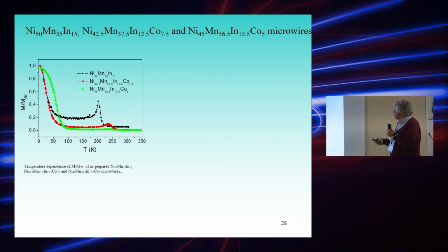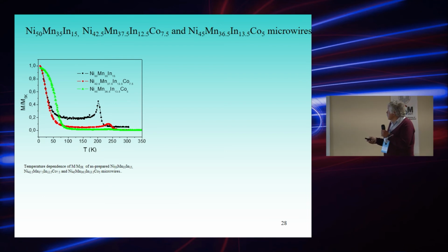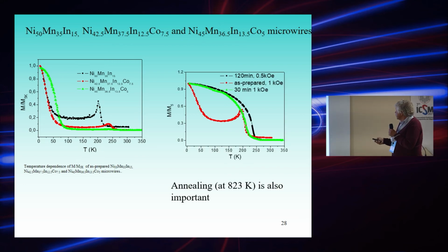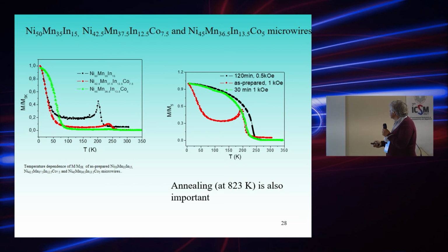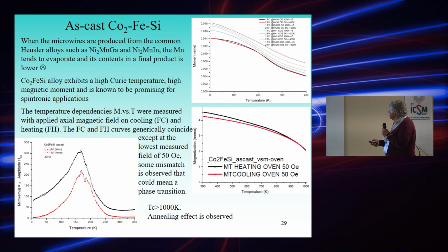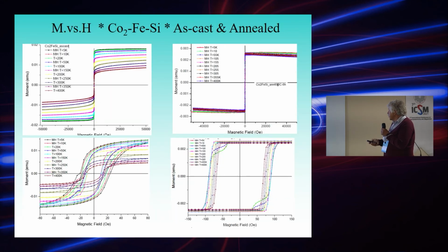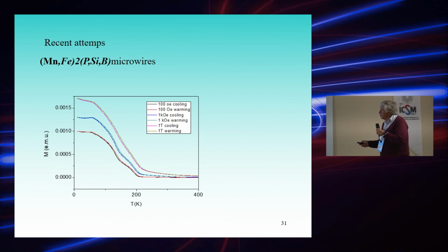So this is an important point, and we tried different compositions. For example, nickel, manganese, indium with cobalt additions, and the features were almost the same. After annealing, we observed nearly room temperature Curie temperature in all the materials. However, we didn't observe a first order phase transition near room temperature. Recently, we tried cobalt-rich materials. They have a high Curie temperature, above the possibility of our PPMS device, so more than 300 degrees Celsius. And at room temperature, they present a squared hysteresis loop with coercivity of about 50 Oersted, which could be suitable for different applications, for example, observation of domain wall dynamics.